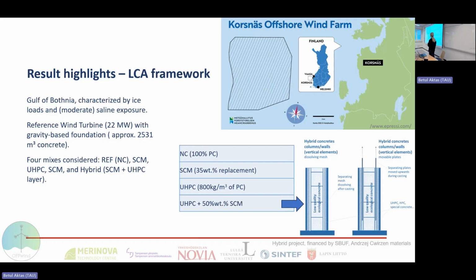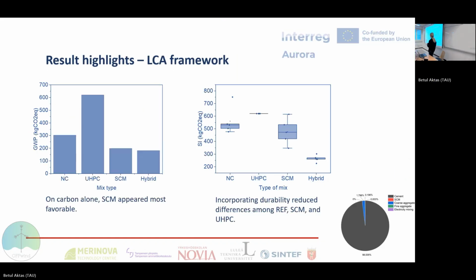And here we not only took evidence for the mixes typically analyzed, which are with replacement of cement with supplementary cementitious materials. We compare them also with ultra high performance concrete, which has very good durability parameters, but also some other types of solutions which we are working on, for instance, involving a hybrid material consisting of UHPC and low carbon concrete with high SCM replacement, to see how their results look when it comes to carbon emissions.